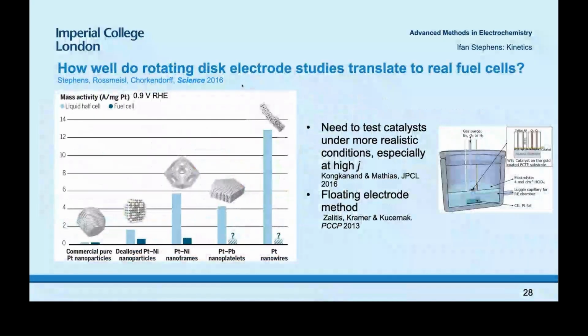However, as Anthony mentioned before, rotating disk electrodes sometimes have drawbacks. In particular, on this plot here we're comparing rotating disk electrode studies to real fuel cells, and we found that some of the really, really active catalysts reported in the literature, for example platinum-nickel nanoframes, when measured in a rotating disk electrode, that's the light blue here, show much lower performance when we measure them in an actual fuel cell. So this calls for testing catalysts in more realistic conditions, for example using a lot of the methods that Anthony described earlier, like the floating electrode method.